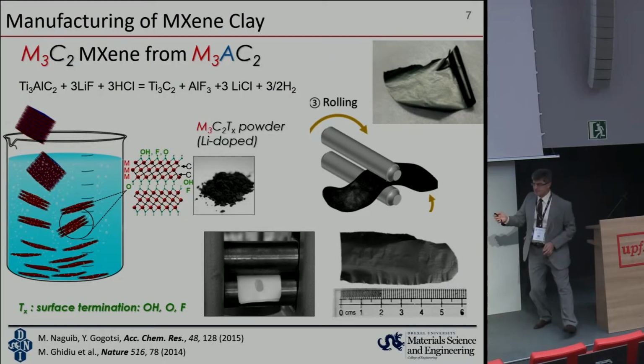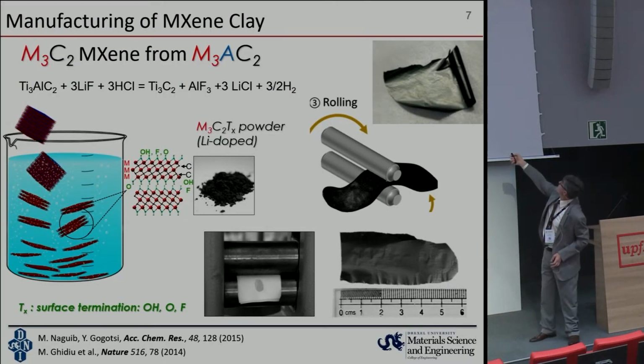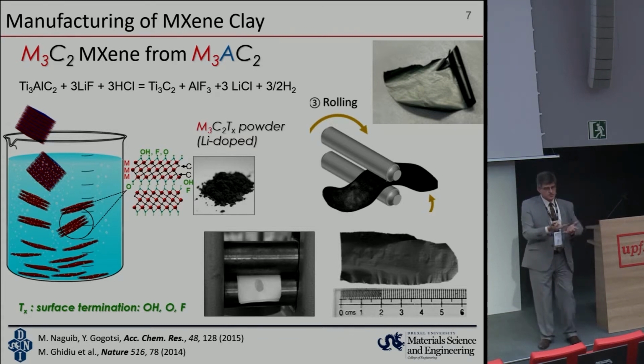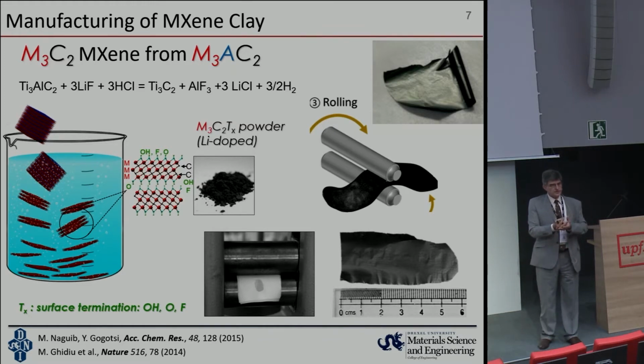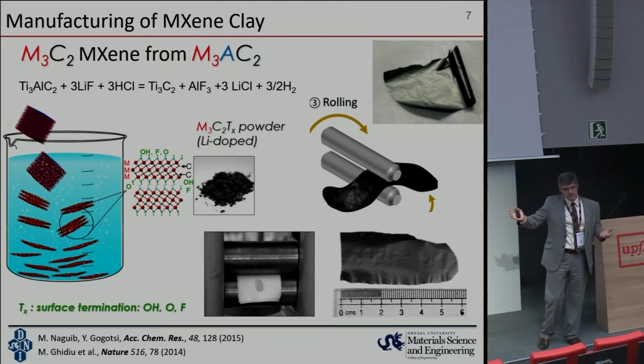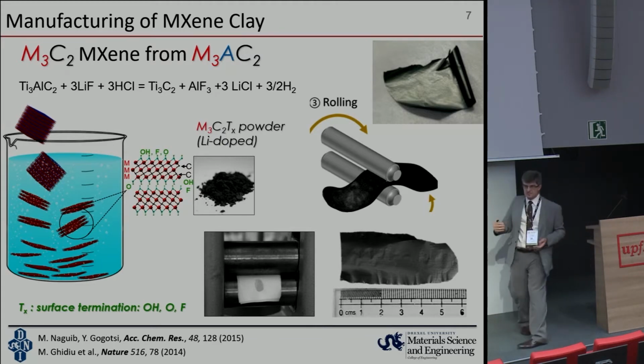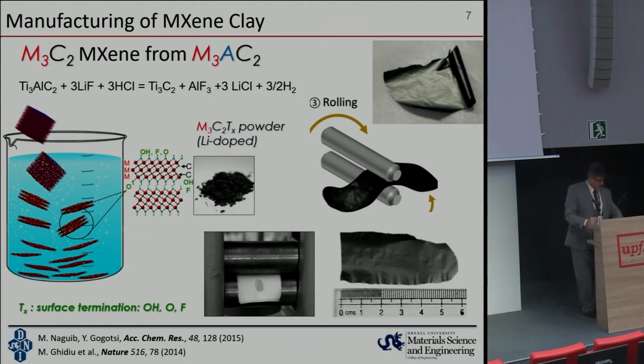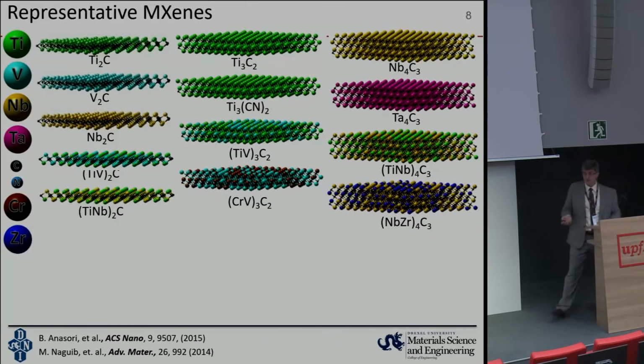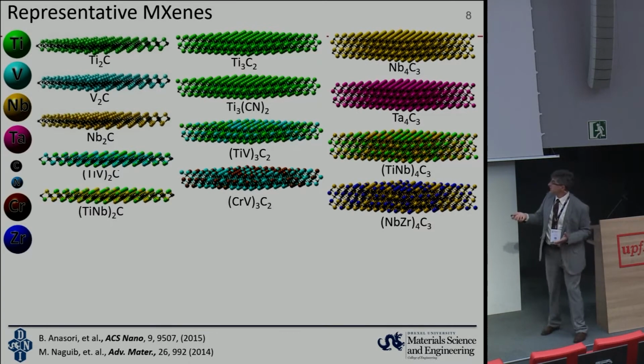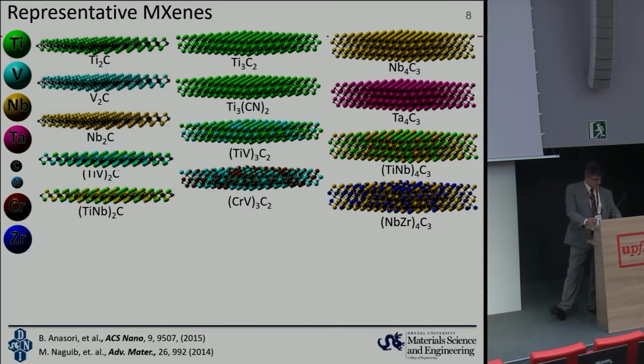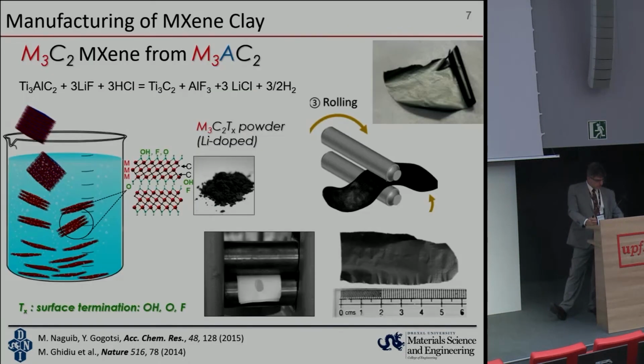Okay, so what you see here. This is a foil. It looks like a metallic foil, but this is just MXene sheets rolled after etching. So within 15 minutes after etching, you produce a foil which doesn't require a binder, doesn't require, of course, any conducting additive here, and looks like a metal foil. So if you're making an electrode, you can right away produce it the same way you would produce an electrode for battery supercapacitors here.